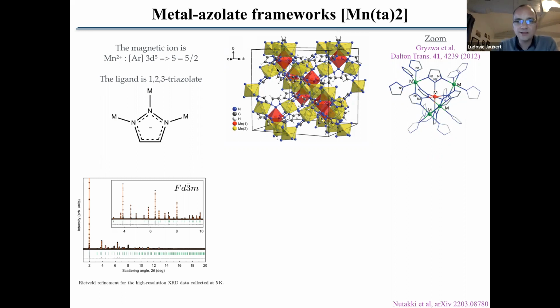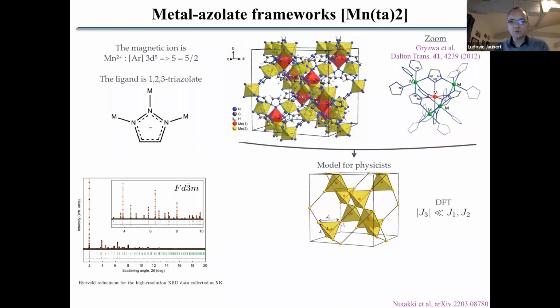So that's how you get a centered pyrochlore lattice, where you have the green ones forming a pyrochlore lattice, as we know and as we have already discussed before, and each tetrahedron has an additional manganese ion in the middle, forming this new geometry, this centered pyrochlore structure. And for us physicists, we can really see this lattice this way, with a pyrochlore lattice and with the centered ion in the middle.